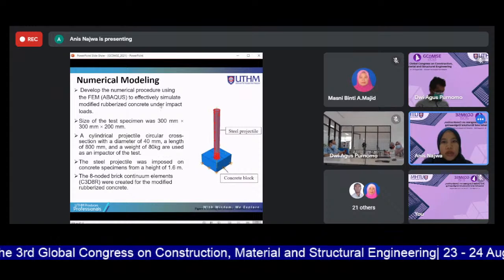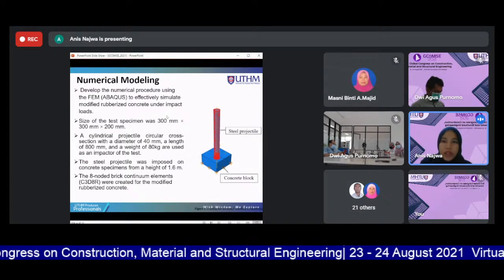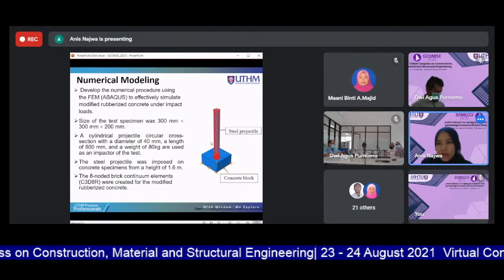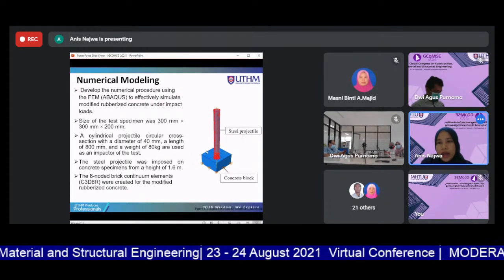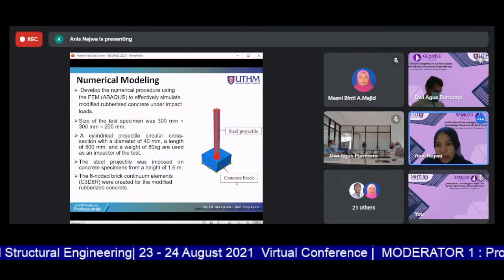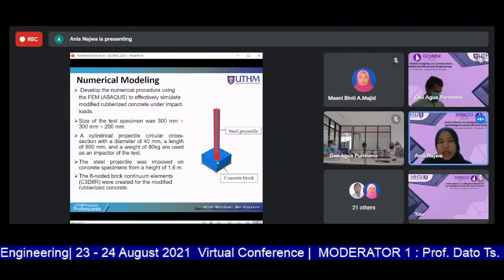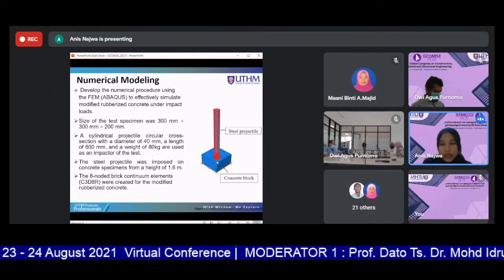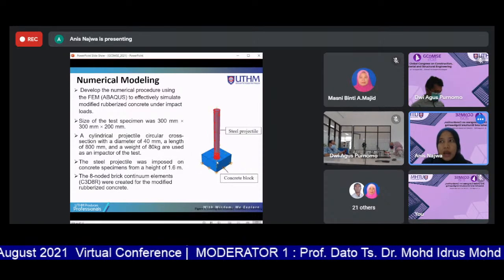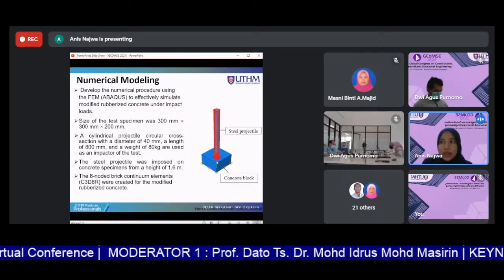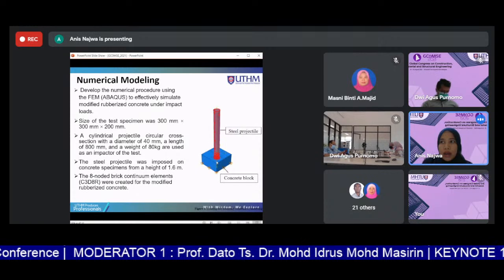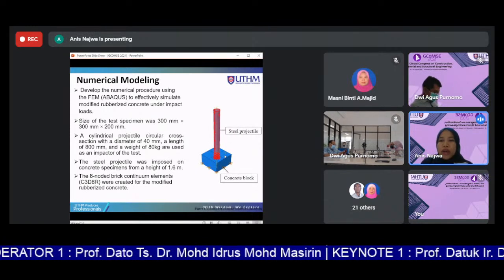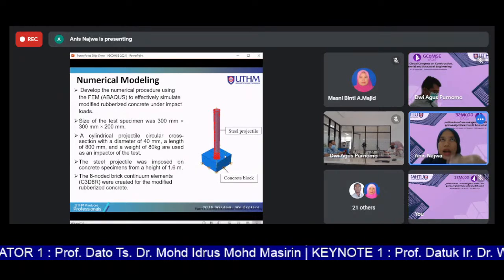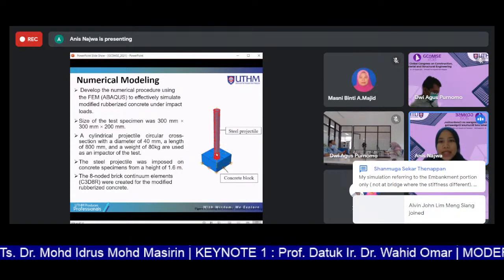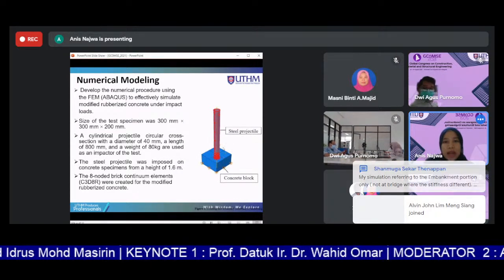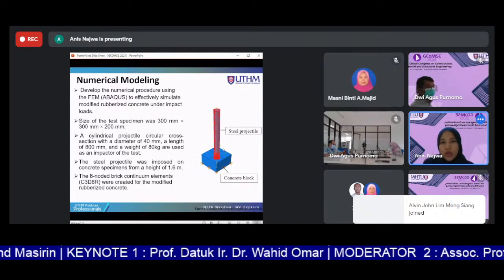So the numerical modeling that has been used is Abaqus software, and this figure shows clearly the sample, which down here is a concrete block. The normal one is the control, with 0% rubber and also 0% rice husk ash. And then it keeps on with the increasing percentage of the rubber. So the size of the specimens is about 300 times 300 times 200 mm.